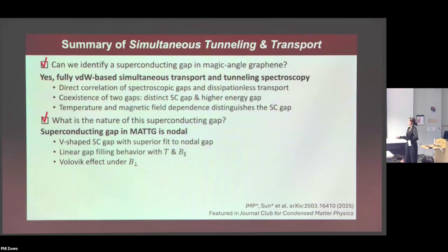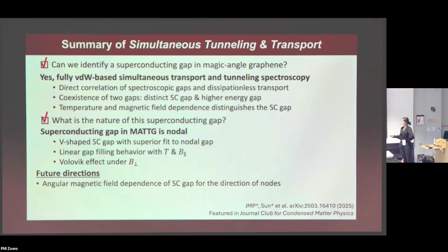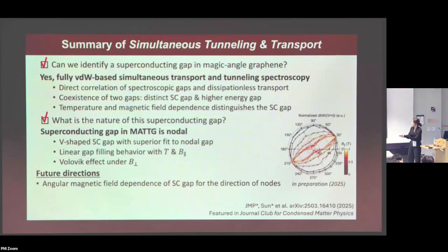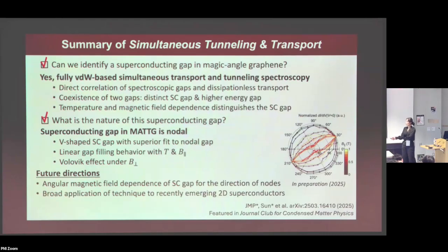So now an obvious next direction is, okay, if you think that the superconducting gap is nodal, can you try to find the direction of the nodes? We can actually do that sort of experiment using the angular magnetic field dependence of the superconducting gap, the in-plane critical field measurements, but using tunneling spectroscopy, and we actually obtained recent results that show very strong two-fold anisotropy in the tunneling gap as well. And this technique is broadly applicable to other kinds of emerging 2D superconductors as well.